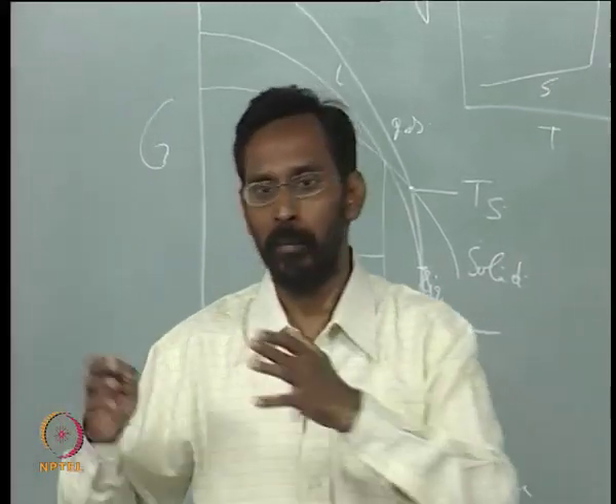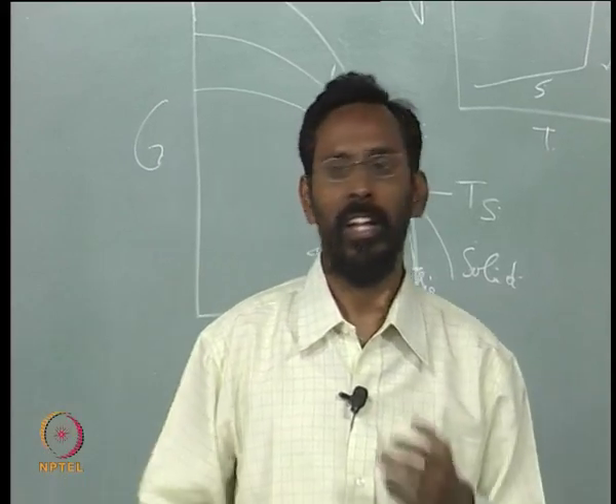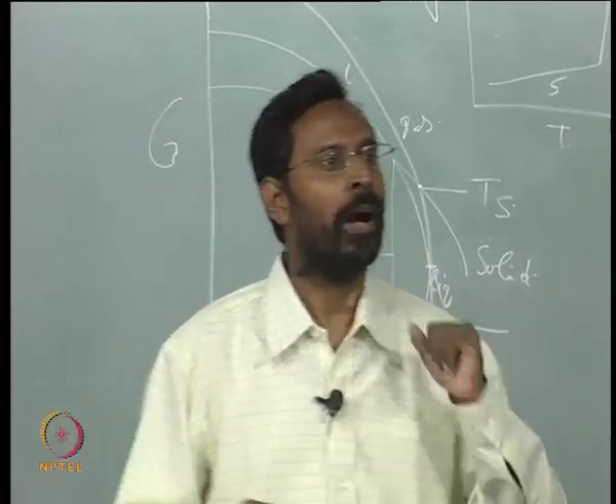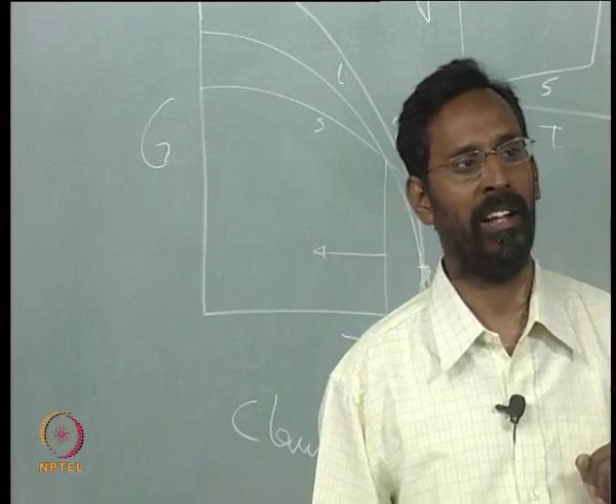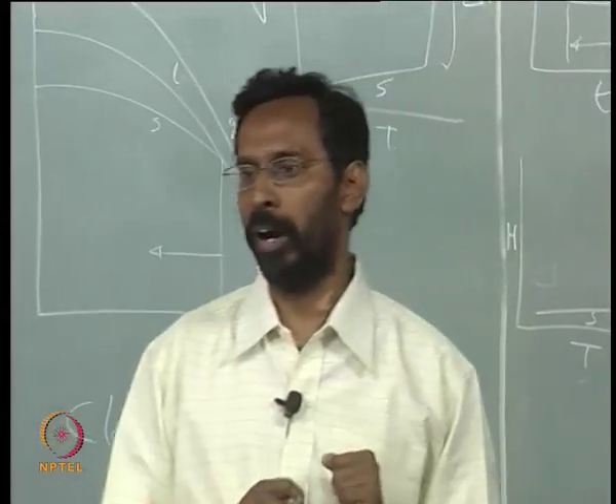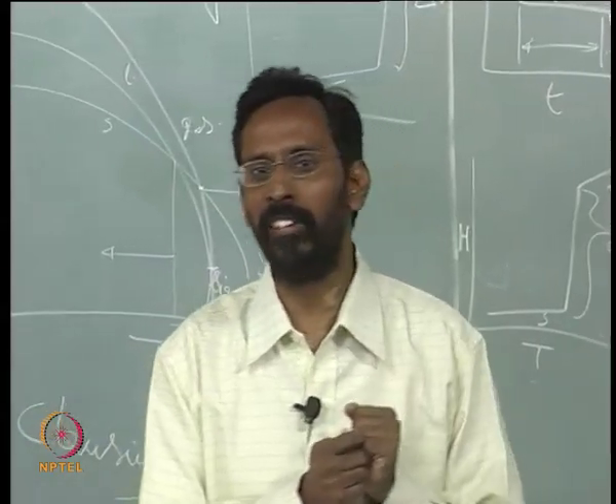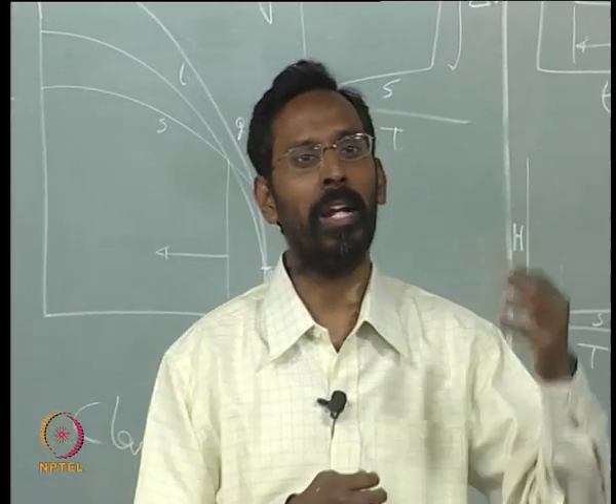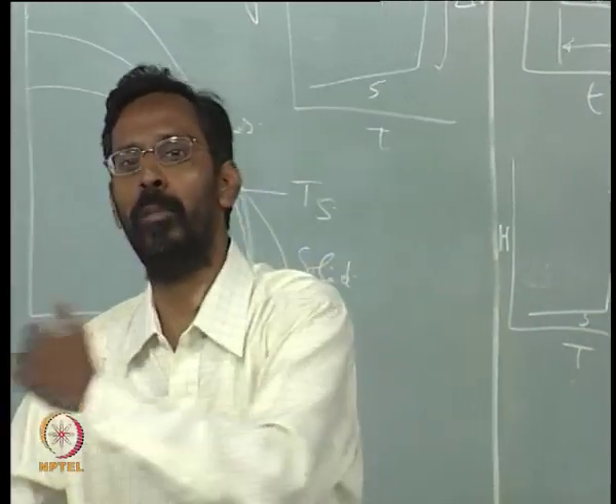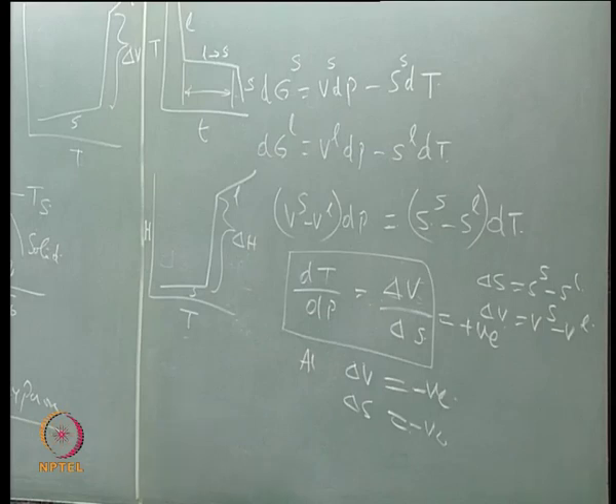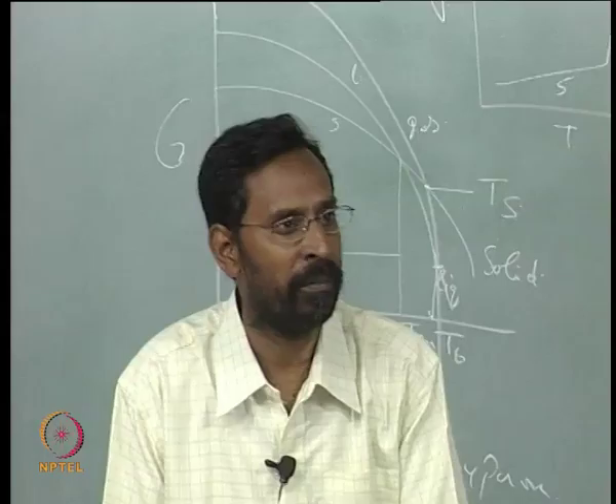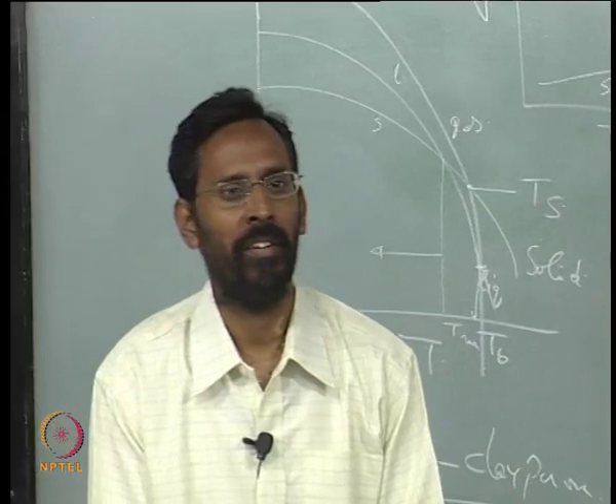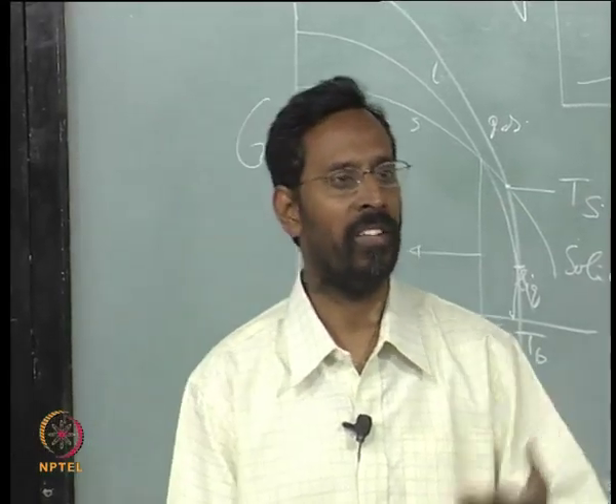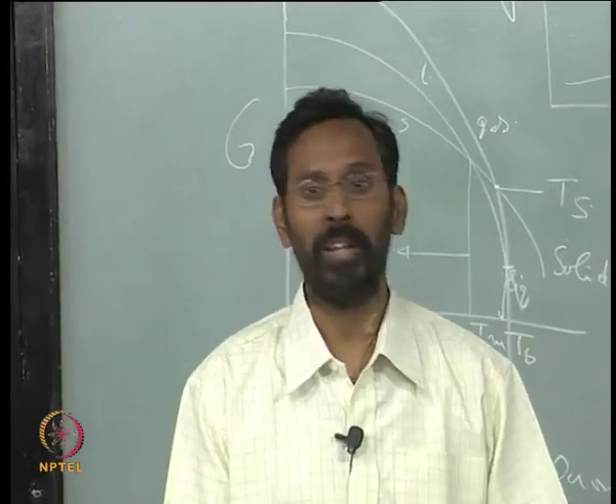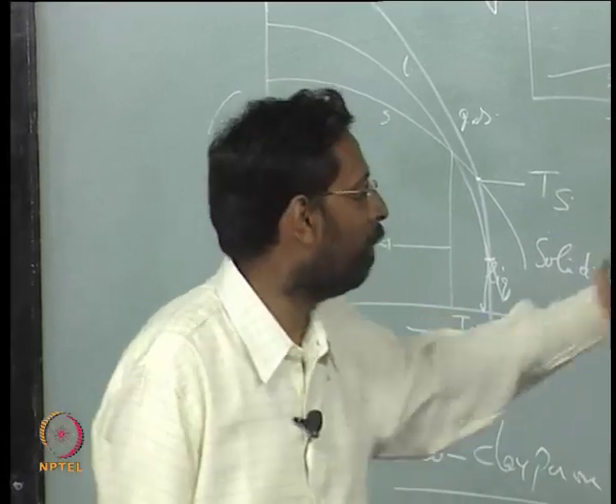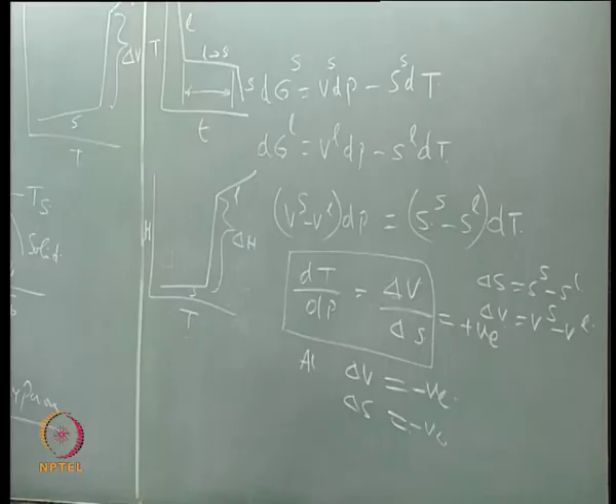So if I melt a grey cast iron in vacuum, its melting point will be higher than its usual melting point, whereas if I melt a white cast iron in vacuum, its melting point will be lower than the usual melting point. Similar thing we also see in case of water and a few other metals. For example, few metals such as antimony, bismuth, they all have delta V being negative, solid to liquid.